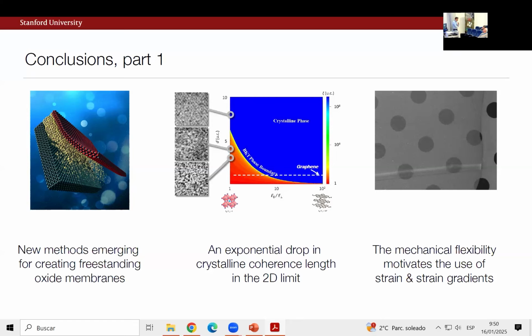If I had to speculate, and maybe go back to these problems, I think we all now have our recipes, right? We all know, or at least I'll speak for what we think we know, that if we have too thick a soluble buffer layer and it's just really fast, it's kind of a mess. Depending on the material stability, the slower you go, the better. I have also been wondering, though it's hard to compare apples and oranges, whether this coherence length scale would be a function of how quickly we dissolve this. How much surrounding lattice do I have to preserve as we go through this? Does it have something to do with how hydrophilic your material is? Could it just be that the water is damaging the STO, whereas for whatever reason bismuth ferrite is more waterproof?